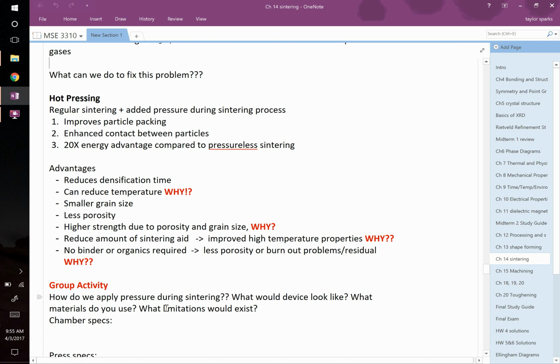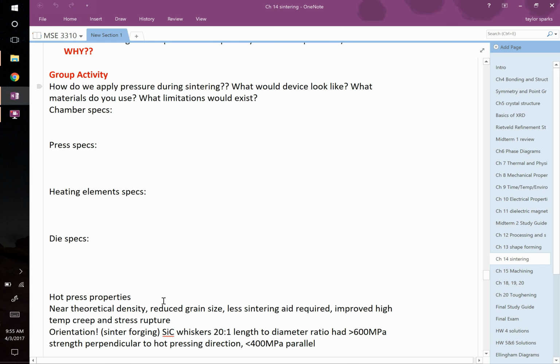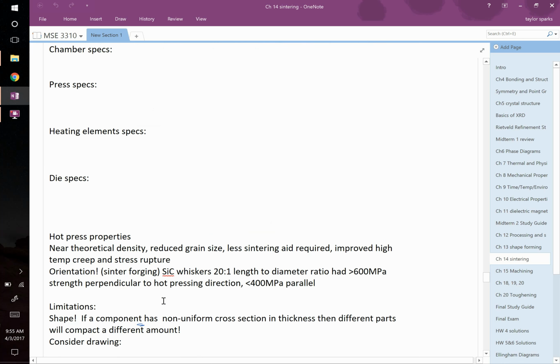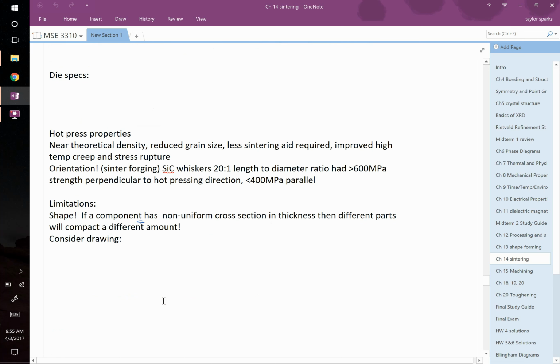What limitations? We talked about that, so let's skip this. All right, so hot press properties: you can get near theoretical density using these things because you're at such high temperatures and you're applying force. Less grain size, no sintering aid, better high temperature creep because you don't use sintering aid, and stress rupture. Another thing that happens, though, is you get orientation.